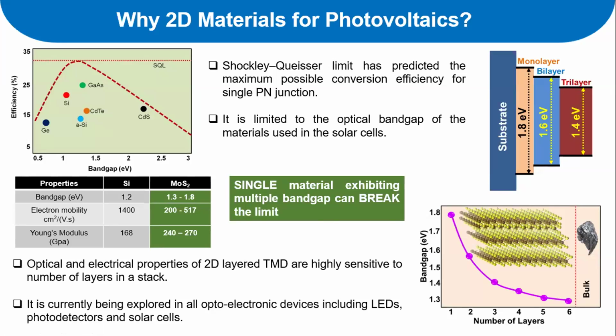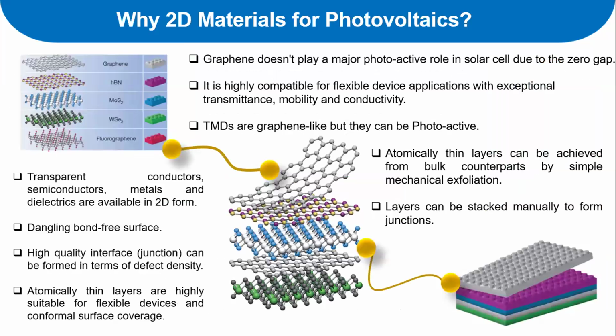In the case of silicon or cadmium telluride or gallium arsenide, that is not possible. The band gap is the same, and if it is direct, it is direct. If it is indirect, it is indirect. We cannot change that for any reason. It is natural. In this particular case of 2D layered semiconductors, the optical band gap can be varied, and the physical nature of the optical band gap also changes. It means direct or indirect. That also can be changed. Okay, so that is the advantage, and these are all 2D layers, hexagonal honeycomb structure materials.